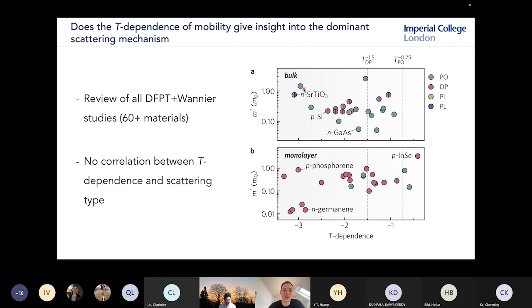And the second thing is that if we take these idealized temperature dependencies that we would have expected from these early theories, I'm plotting them here for deformation potential scattering, so this is minus 3/2, and the polar optical phonon scattering. If these had any predictive power, we'd really see the points clustered around these lines, and you can see that there's effectively no clustering whatsoever.